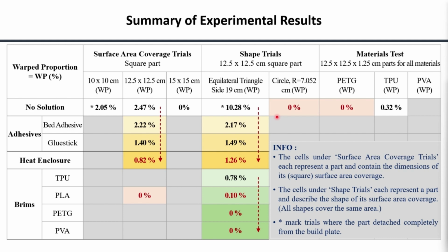Finally, we have the materials test, where PETG showed promising results by having a warped proportion of 0%. I even printed a triangle part with PETG, and it still experienced no warping, though that isn't listed on this table. Now, moving on to the solutions tested. Generally, bed adhesive reduced warping the least, while the heat enclosure reduced warping the most, if excluding brims. However, when including brims, they consistently perform better than the previous solutions, being able to completely resolve warping in some cases. PETG and PVA performed equally well as brims, completely resolving warping, while PLA performed slightly worse. TPU was the worst at preventing warping, but even then, it reduced warping more than solutions using adhesives or the heat enclosure.